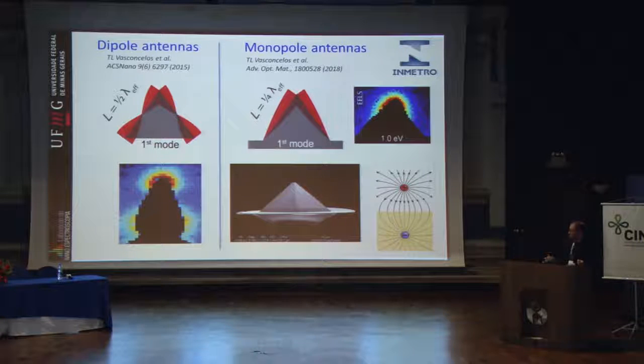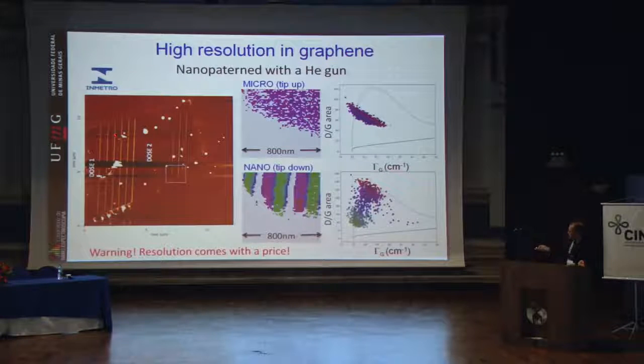And with this kind of technology, we now have tip-enhanced Raman available with the efficiency that one needs to do, for example, this: a piece of graphene, okay? And we come with a helium gun, and you make cuts on the graphene with helium. And of course, if you take this square here that is 800 nanometers, and you try to image this square with optics, Raman imaging, you will not see anything specific related to the lines because this is about the size of the laser spot itself. So it doesn't matter if you keep moving here, you're moving a huge spot. And when you try to look at what the defect is here, you will see something that is an average.